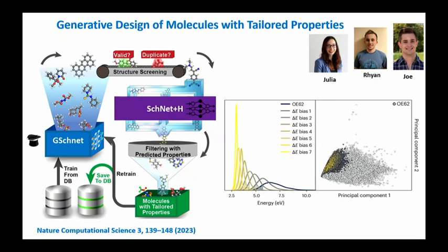And every time we do it, we basically bias the model to give us more and more molecules with lower and lower fundamental gaps, to the point that we now have a distribution that is outside of the original distribution of properties that we had. Initially I found that a bit worrying, because it means the model is now extrapolating and you don't know what it's predicting. At every step, of course, we take a few data points and redo the GW calculation to check that our predictive model is still valid in that regime. So it remains in distribution for the properties.